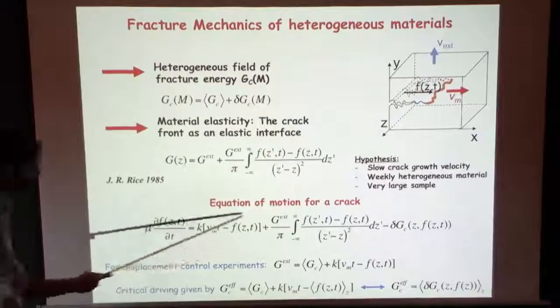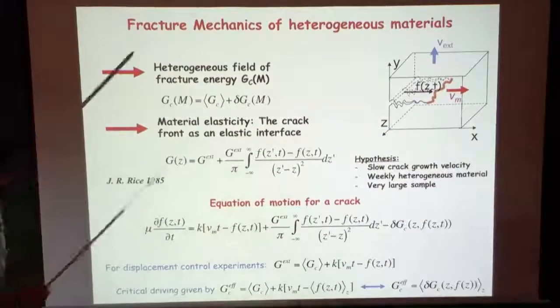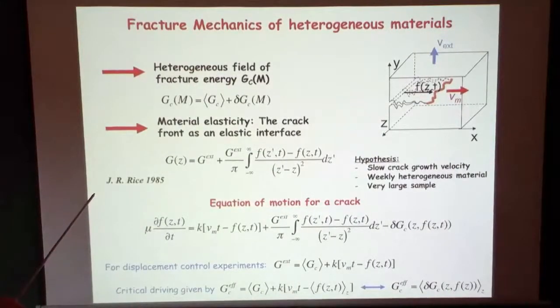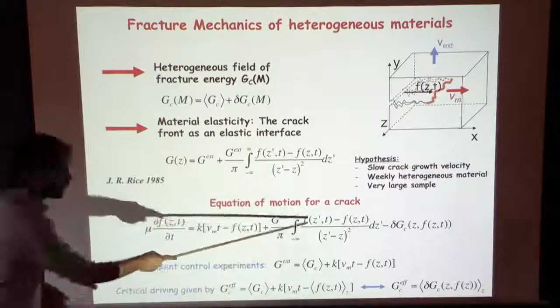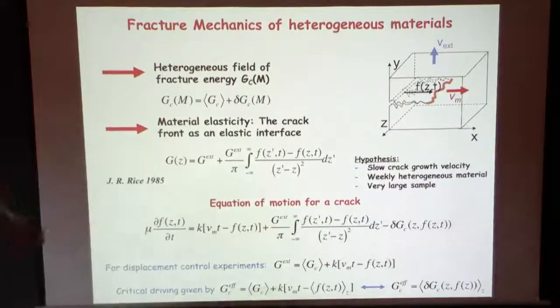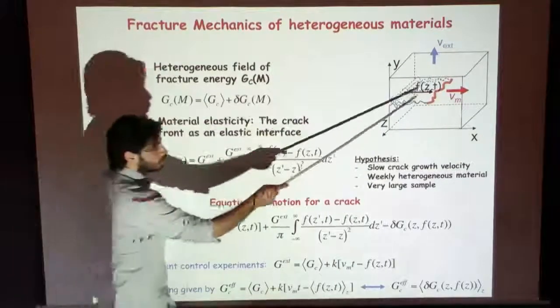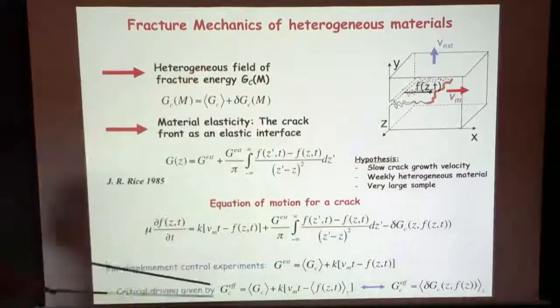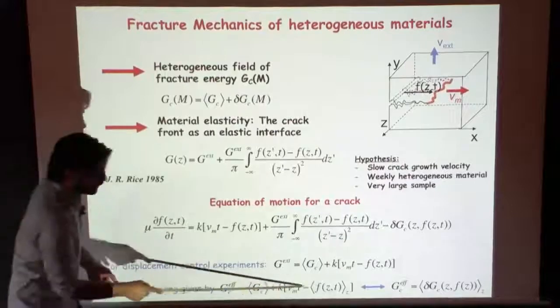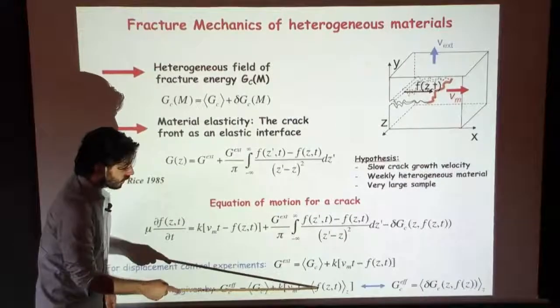So this gives you an effective driving through springs, and also from this equation you get the spatiotemporal evolution of your front, but you get also the driving. If you pull at constant velocity, you don't impose the force at which you pull on your sample, you predict it. And you predict it using this formula that is the distance from the position of the rigid bar pulling on the line to the average position of the line.